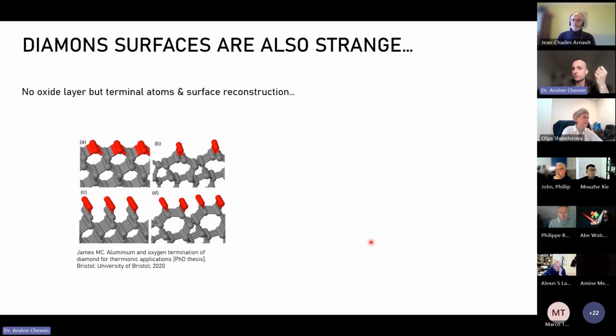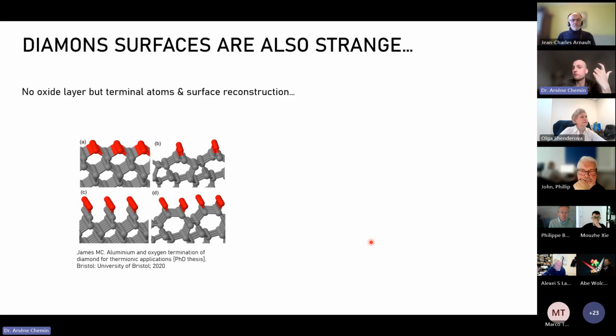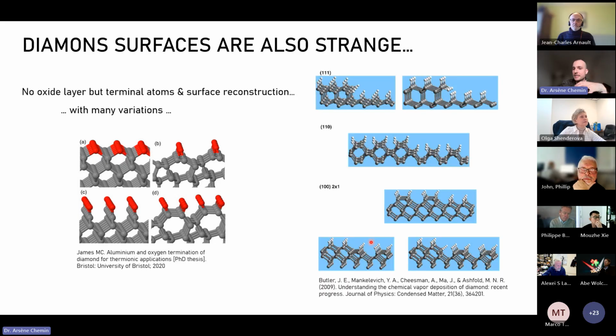And you can also have surface reconstruction, meaning that different carbon atoms will bind together, forming some sp2 bonds instead of the classic sp3 bonds of diamond. On top of that, you have many different facets that can lead to different bonding configurations. But of course, you also have some facets that can be cut in weird ways, with some jumps and some stairs cut in different crystallographic planes, leading to even more possible bonding environments of the surface states.